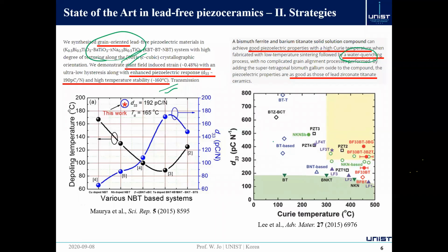I've never seen the samples they produced, but we tried to repeat the experiment in our laboratory. We found that, at least from scanning electron microscopy, there were a lot of microcracks. Of course, piezoelectric is an electromechanical material, which means it vibrates all the time, so microcracking should be a big problem. So this is a brief review of the state of the art.